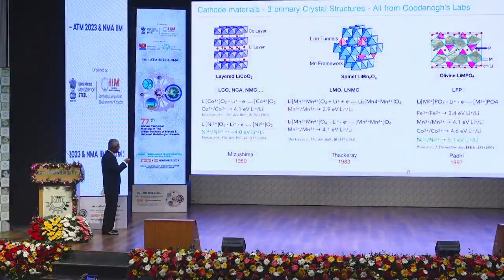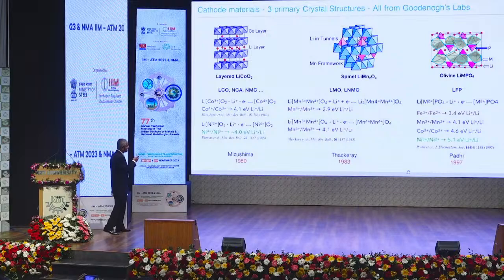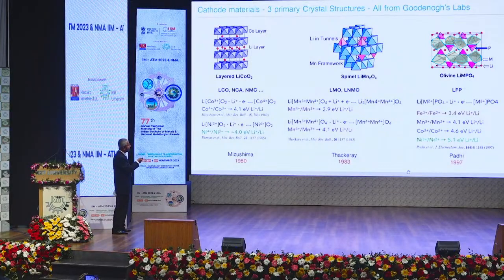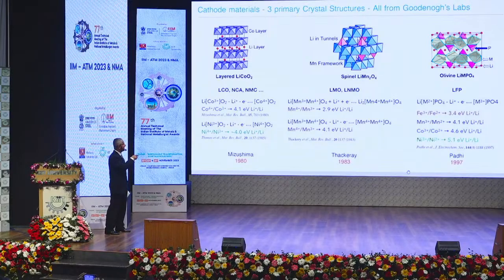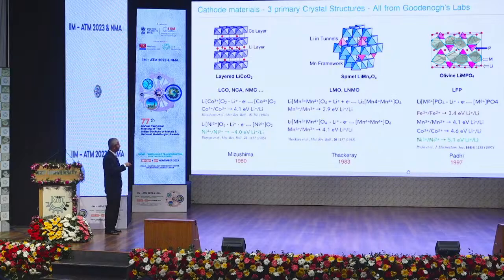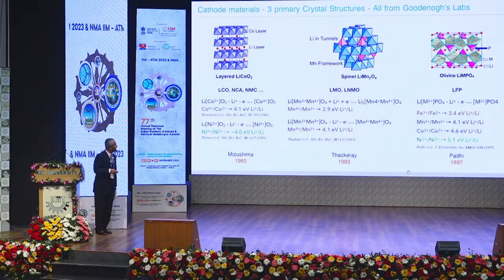So in 1997, I identified this particular structure, the olivine structure, LiMPO4. Olivine is actually a magnesium silicate, but we can make it with lithium and a metal on the magnesium site and phosphate for the silicate groups. So we identified this and we called it phospholivines.